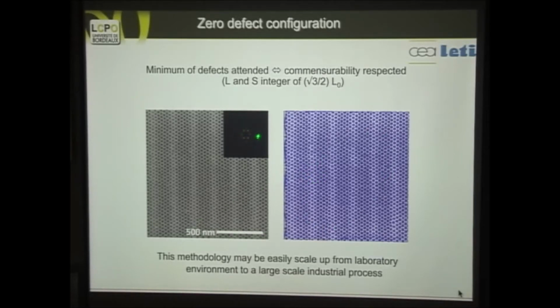And you see also by the Fourier transform of this pattern, we have not only the first order diffraction of this structure, but we have higher orders, which means that the single crystal of this material on the surface is enormous. We see some reminiscence also of these spots that represent the periodicity of this wavy pattern that we put below. But eventually when we put the thickness a little bit higher, then it will disappear completely.